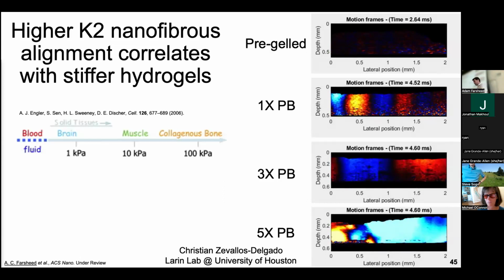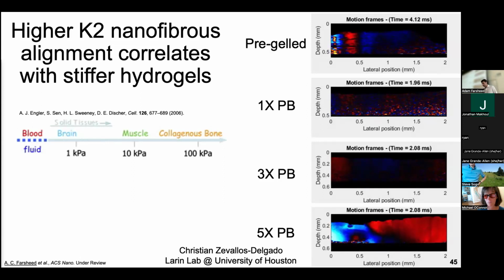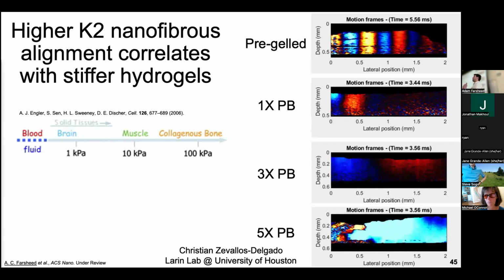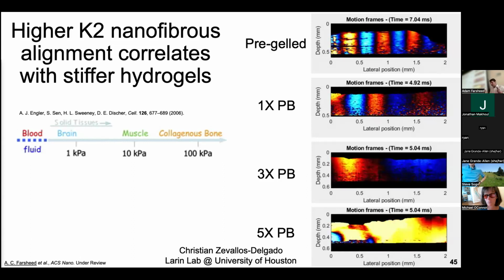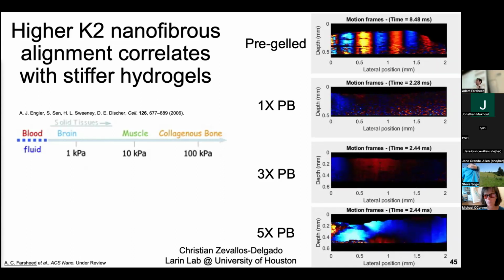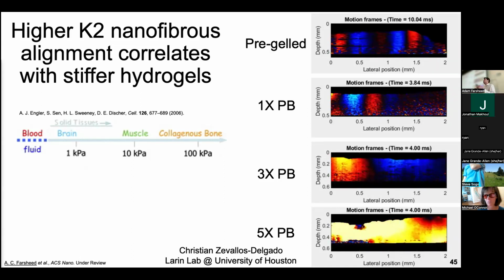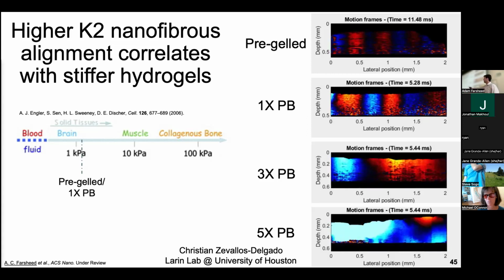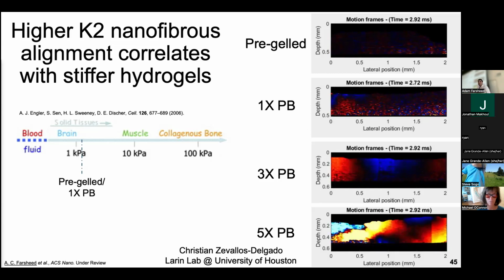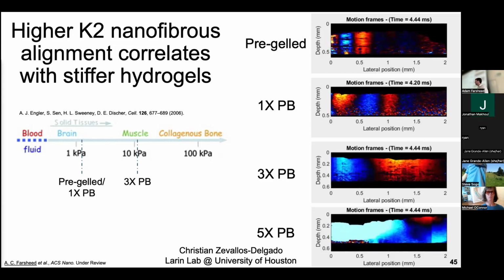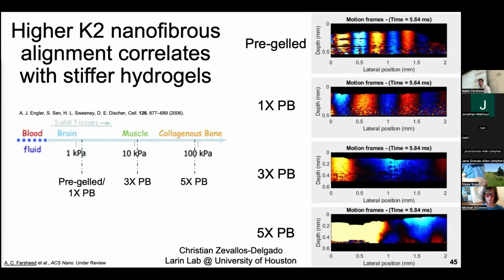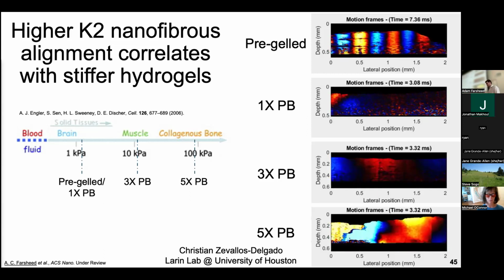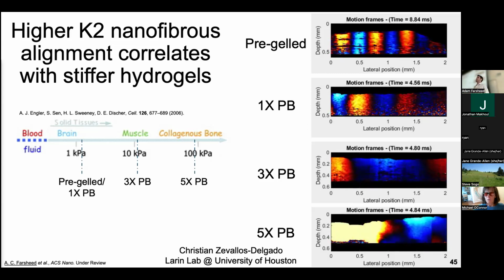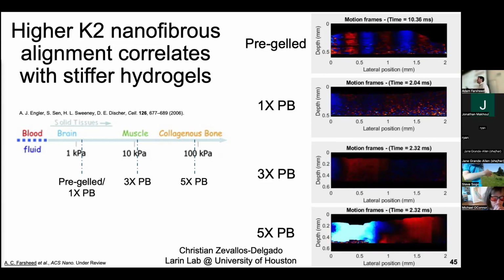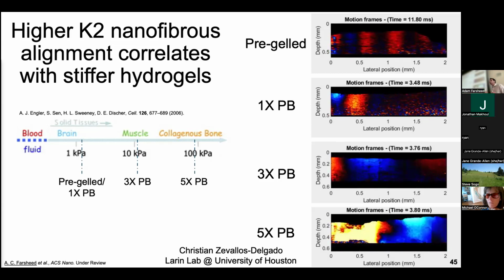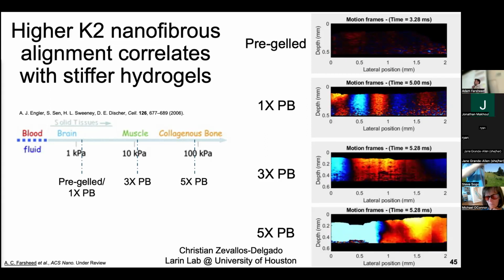And just to orient us, what does this look like in terms of the tissues in our body? Well, first, I just want to say that we're going to make some pretty big assumptions that we know are not actually the case, where we're going to assume that our system is isotropic, so that this anisotropy doesn't actually happen, to be able to get the bulk stiffness understanding of our material. And so in this spectrum here of different stiffness values, our pre-gelled and 1xPB noodles fall somewhere close to brain tissue, whereas our 3xPB noodles fall close to muscle tissue, and our 5xPB noodles are approaching bone tissue. Now, I do want to again emphasize that this is not an apples to apples comparison because we're again assuming that the strongest part of our system is the strength in every which direction. But it is pretty cool that without changing our material, we're just changing the way in which we're extruding and processing our material.